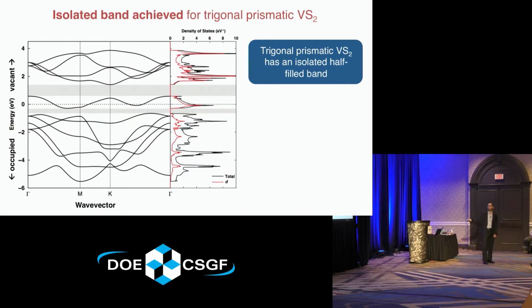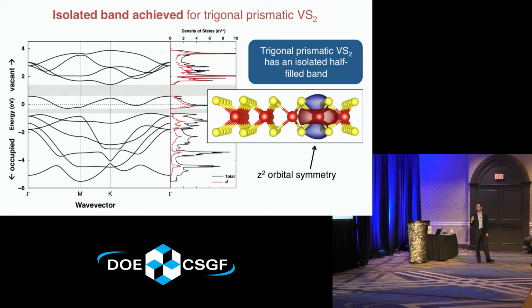If you integrate over all of the wave vectors, you get the overall electronic spectrum, which just indicates that this is a d orbital, and in particular, it's this dz squared orbital. So you have one kind of lobe, and then you have a donut going around it. And so we are able, with trigonal prismatic VS2, to achieve this one-band correlated material, this rare property of the cuprates. So we wanted to understand this a little better to see how we were able to achieve this rare